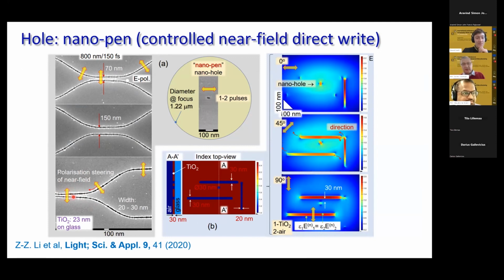Yes, this will be defined. In this case, we used 20 nanometer film, so it was opening of 20 nanometer wide grooves in 20 nanometer thick film. If the film is thinner, you can very nicely open a smaller groove. So this is basically also defined by the film you are depositing on the surface, and certainly the precision of that first opening of your ablated hole in 1 or 2 pulses, because this is your writing pen. Once you have it smaller, you can reduce pulse energy in such a way that you are not modifying anything else, and the only modification happens because of light concentration in that groove. So the short answer would be that it's mostly defined by the thickness of your resist. If you want a smaller groove, and if you want to write them closer, your resist should be thinner.